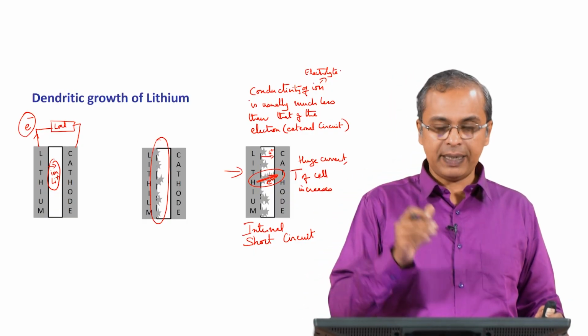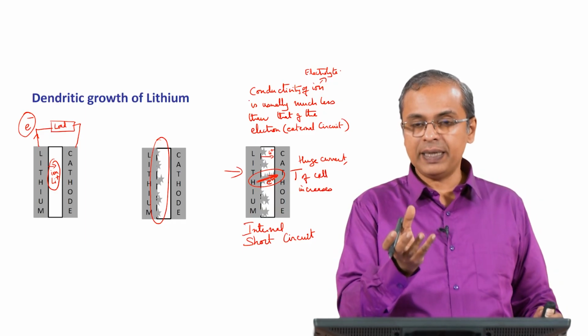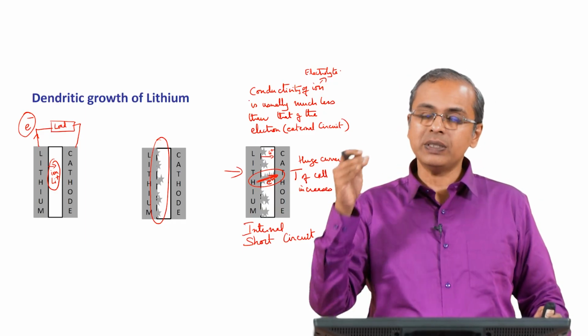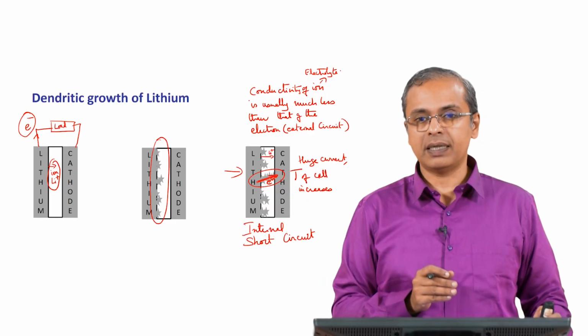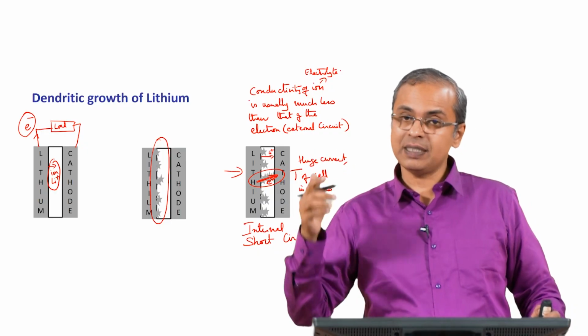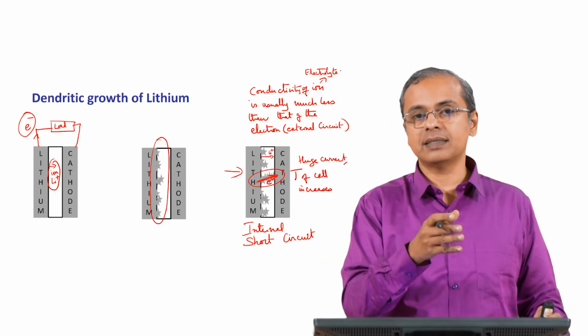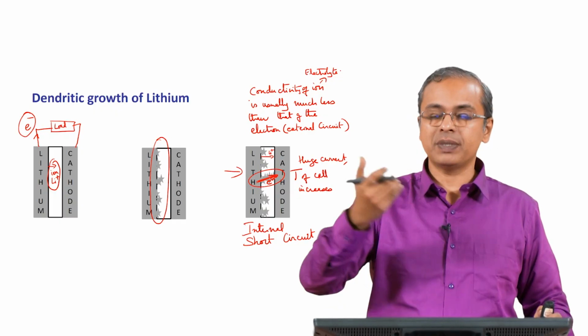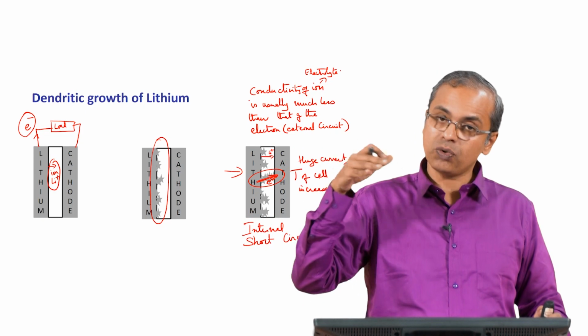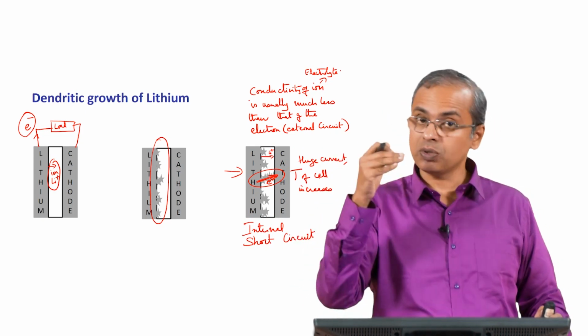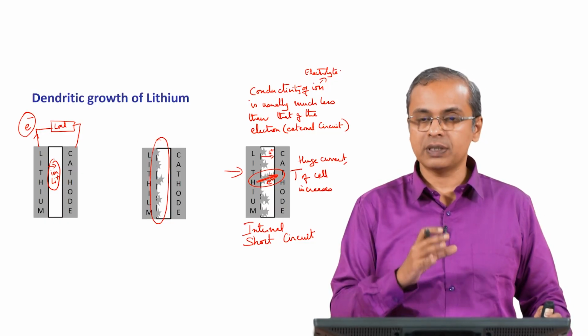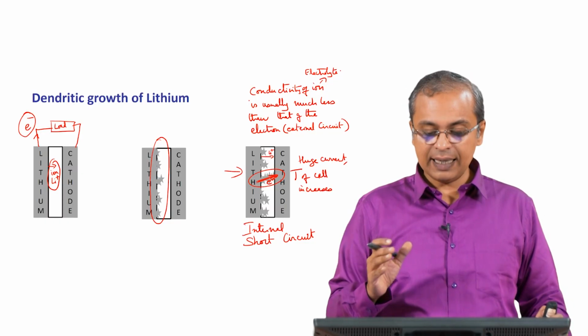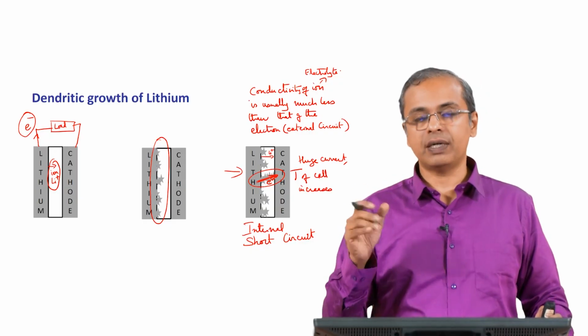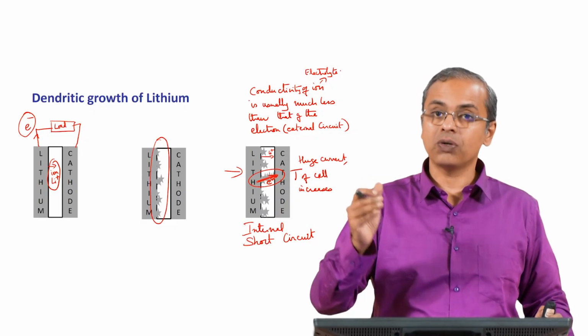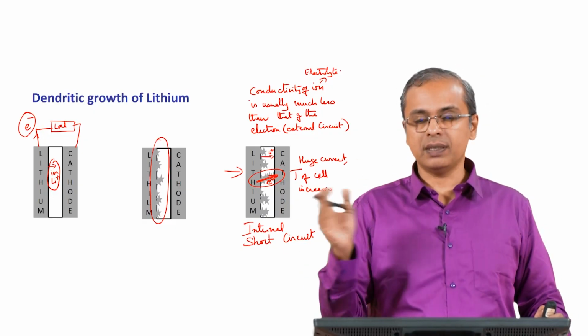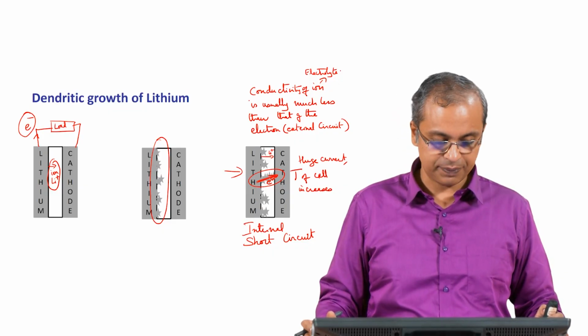So, instead of putting lithium metal, they started to look for other materials which are then called host materials, inside which lithium can sit at a potential very close to the lithium metal potential. So, now the lithium is not sitting on the surface, it is actually going into that structure and sitting inside that structure, and then when you discharge the cell, it is coming out from that structure to complete the reaction. When you recharge, again it goes back into that structure. Okay. So, it is not on the surface, it goes inside the structure. So, that kind of a host material began to be used as the anode as opposed to lithium, and in that case you never have lithium in metal form, you only have it in ionic form, and that is why the new generation batteries are called lithium ion batteries. The lithium stays ionic throughout the circumstances that it is presented with.